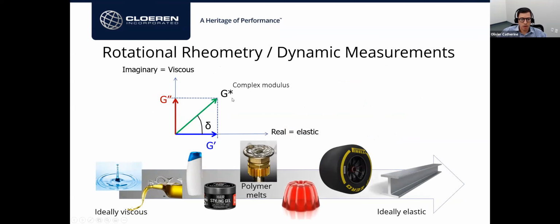So for example, the modulus that we are measuring during this, which is derived from the torque measurement, is composed of a real part and an imaginary part of the complex modulus, where the real part is linked to the elastic behavior of the material, and the imaginary part is linked to the viscous behavior of the material. So here on this scale, I represented a typical behavior from liquids to solids, with a gradual increase in elasticity. And polymer melts are really a true viscoelastic material, meaning that both elastic and viscous components are important, and that importance is going to vary as the frequency is changing.